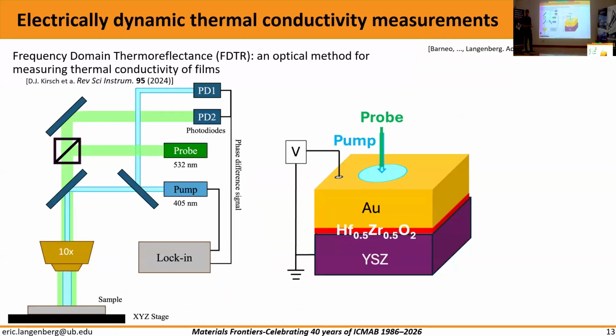And then we measure the thermal conductivity with an optical technique, a pump-probe technique, which is frequency domain thermoreflectance. And we deposit gold on top of it, and we measure the thermal conductivity of the whole structure and compute the thermal conductivity of our hafnium zirconium oxide.